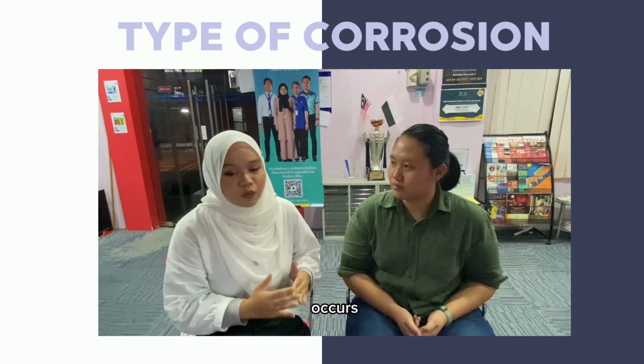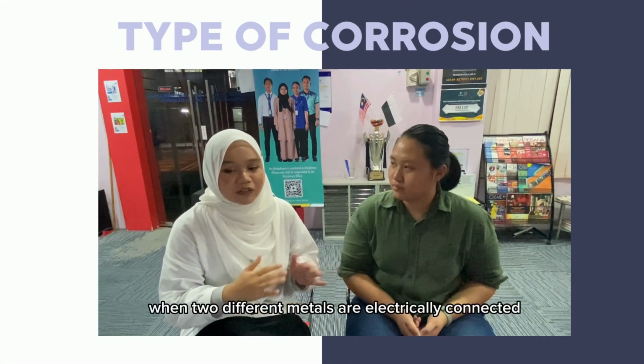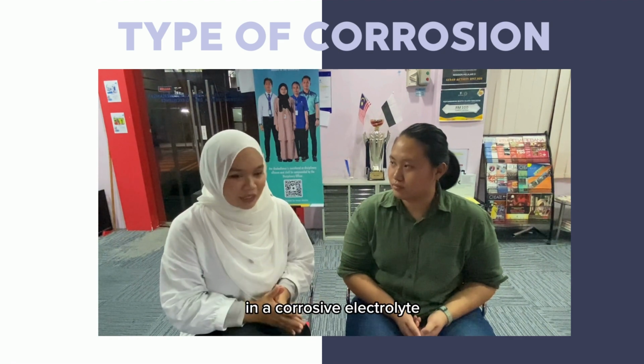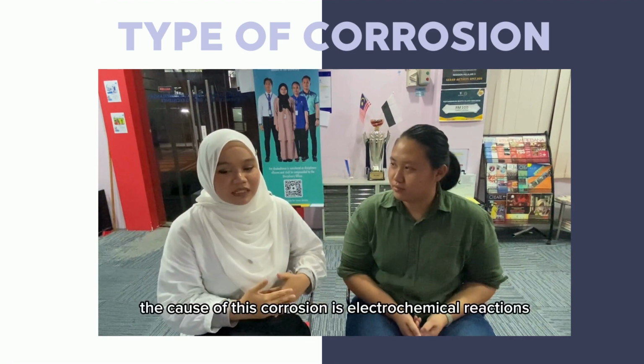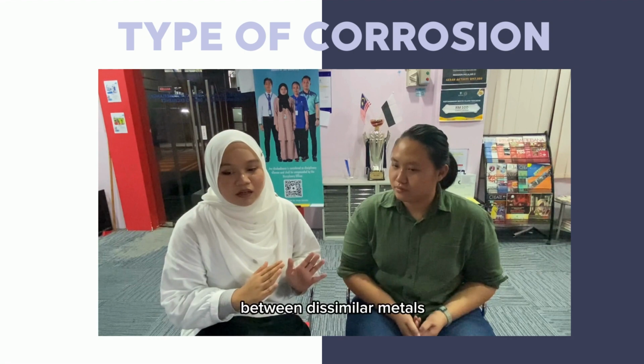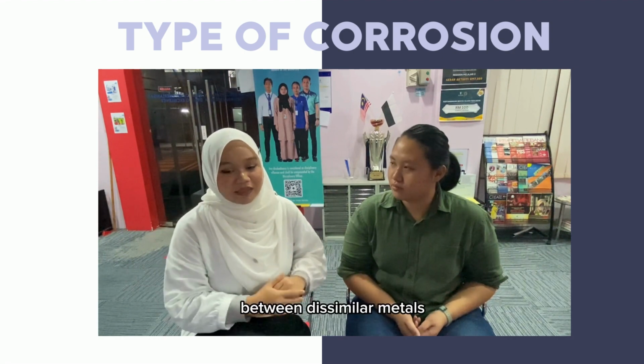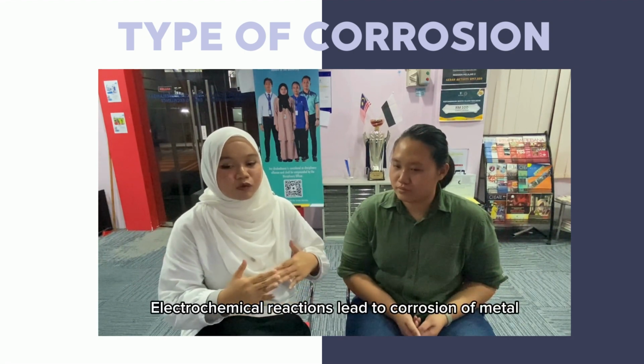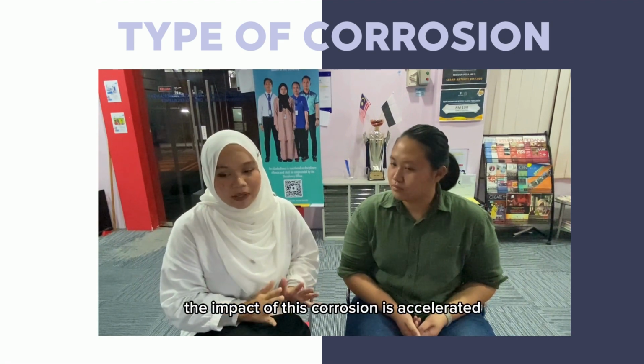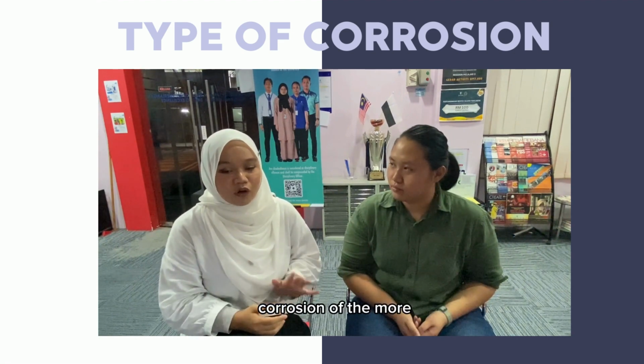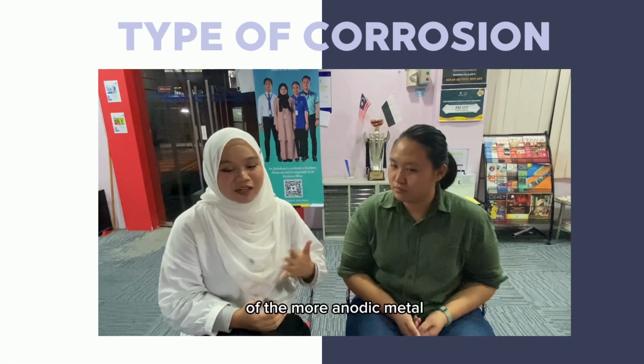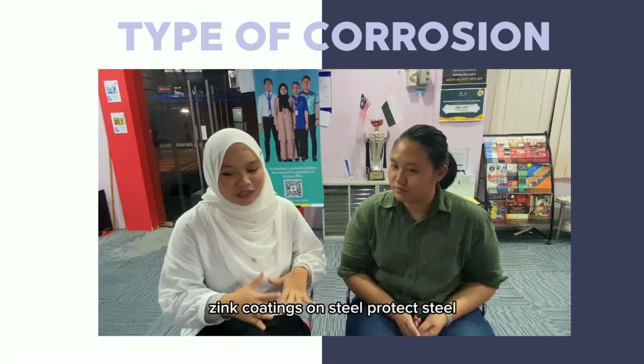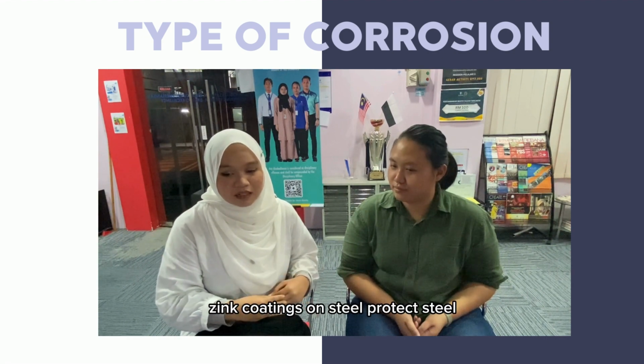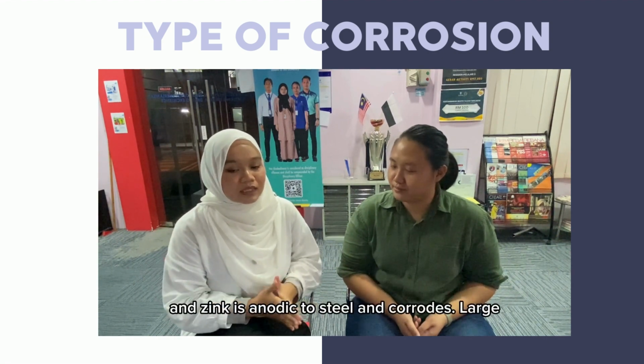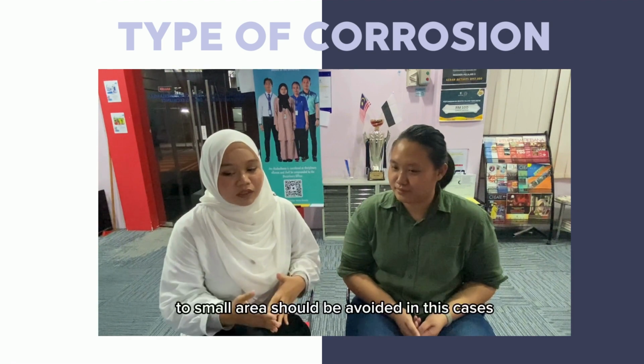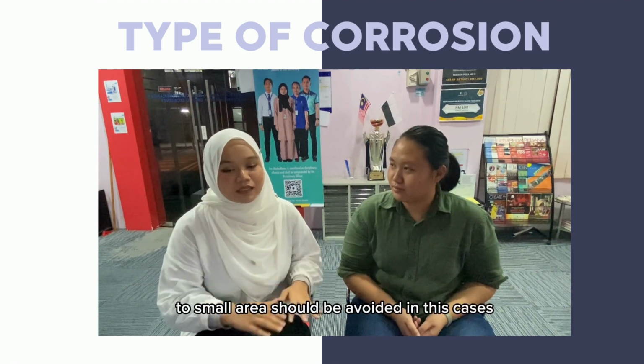Then, another type of corrosion in the refinery is galvanic corrosion, which occurs when two different metals are electrically connected in a corrosive electrolyte. The cause is electrochemical reactions between these dissimilar metals, which lead to corrosion of the metal. The impact is accelerated corrosion of the more anodic metal. Zinc coatings on steel protect the steel, as zinc is anodic to steel and corrodes. Large cathode areas with small anode areas should be avoided in these cases.